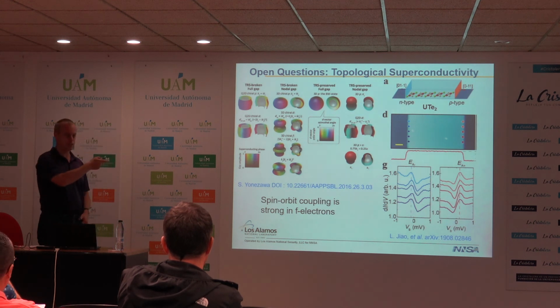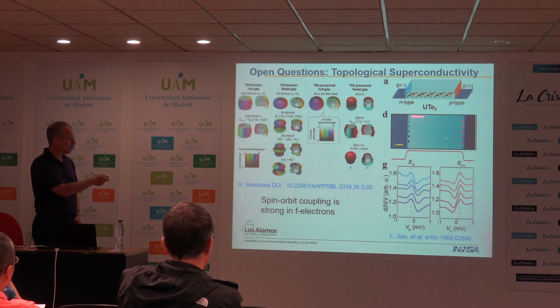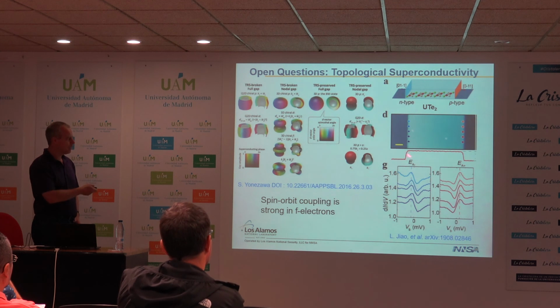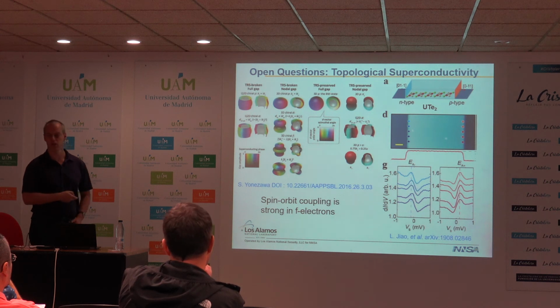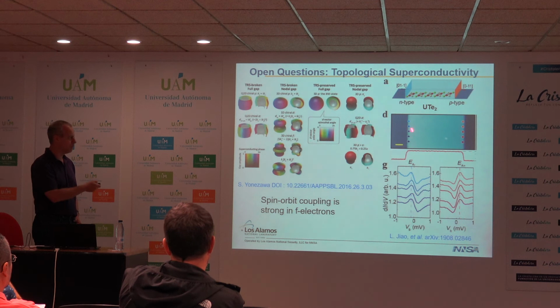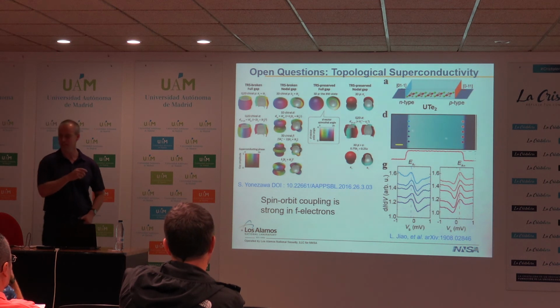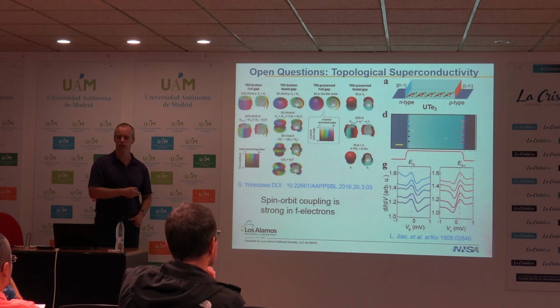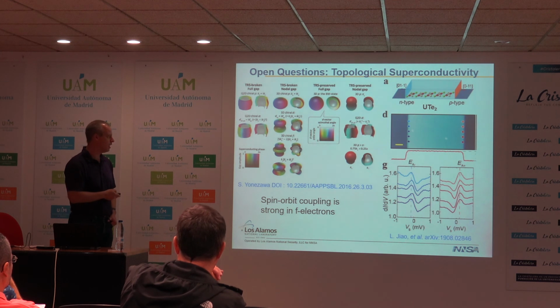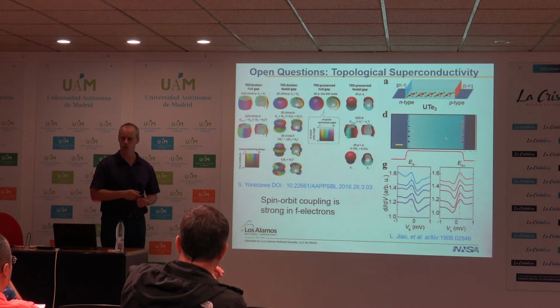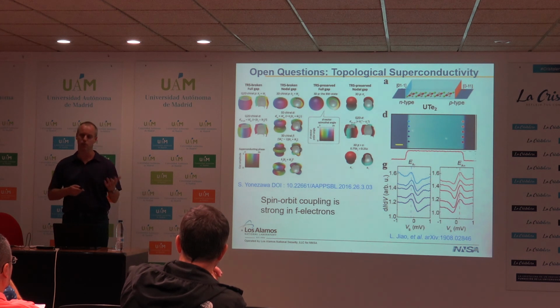And I'm not sure how much Alexander will talk about this in the next talk, but there are some interesting results on a very new superconductor. This was just discovered last year, uranium-tellurium-2. And there's some STM work by Vidya Madhavan where they're looking at step edges on the system, and they claim evidence for chiral edge states on these step edges. So I'm sure this is still controversial, and I certainly can't defend it, but I think it's a very interesting direction to go in these materials. And there are other systems, UPt3, uranium ruthenium-2 silicon-2, for which there are concrete proposals on topological superconductivity. We now need to find the right tools that will be able to find the signatures of the topological superconductivity.